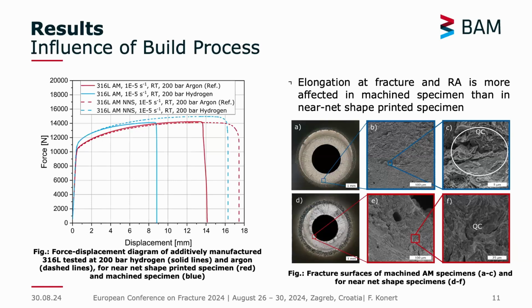But then afterwards, the contour was machined in outer geometry. And as you can see as well in the force displacement diagram, also in the fractographic images, for the near net shape specimen, you have a clear, or a slight, decrease in the elongation at fracture for hydrogen, but it's not nearly as big as it is for the conventionally manufactured geometry of the additive manufactured specimen. But there's still a hydrogen effect present in both.